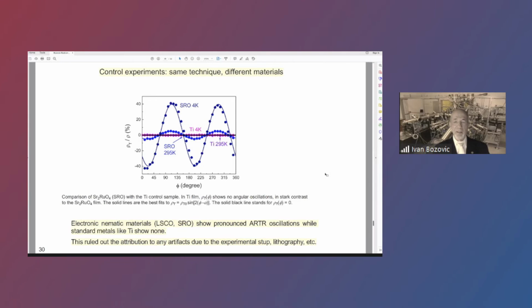And in contrast, in titanium, that's this purple curve and purple line, it's completely flat. There is no signature of oscillation whatsoever on this scale. And this is another logical check because it rules out artifacts from the experimental setup or lithographic mask, substrate, etc.